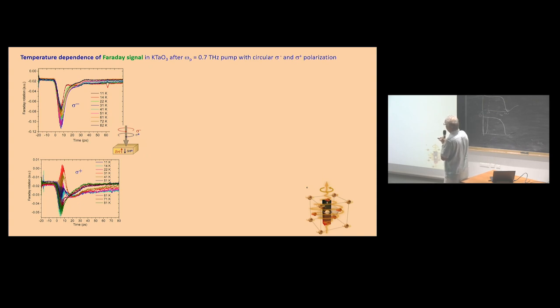So when we had a left-hand circular polarization, we see such a peak here. I have to stress, our pumping was not a single pulse, but it was 10 picoseconds long. So then we have relaxation. Here is the increasing signal, and then we have relaxation. But when we use sigma plus, it means right-handed pumping, you can see the change of sign of this rotation. So it is evidence for magnetic induction in this case.